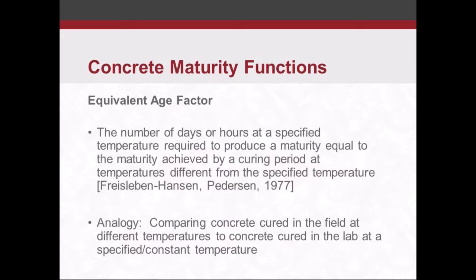There's another maturity function that's called the equivalent age factor. It says a number of days or hours at a specified temperature required to produce a maturity equal to the maturity achieved by a curing period at temperatures different from the specified temperature. An easy way of saying that, or something analogous to that, is comparing concrete cured in the field at different temperatures, right? The temperatures fluctuating in the field, to concrete cured in a lab at a specified constant temperature. So that's what this particular maturity function would do. Compare concrete cured at a specified temperature to the time and temperature conditions of your concrete out in the field.